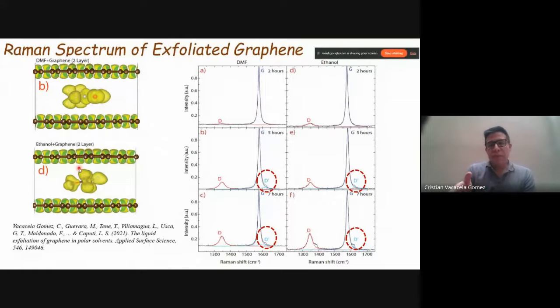But note, we can remove these solvent molecules, for example, by working with the boiling point. For ethanol, it disappears after 60 to 70 degrees. So this is the model we propose for the exfoliation process of graphite using two different solvents, DMF or ethanol. But the important thing here is what happens with the Raman spectrum. If you remember, the idea is to reduce the sonication time in order to get a few layer graphene dispersion with high quality and high concentration.